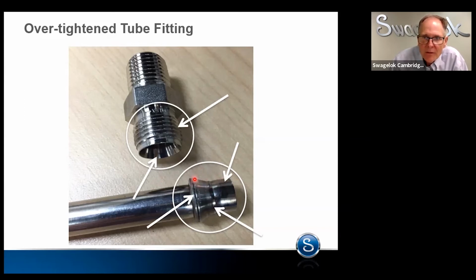But when you've over-tightened a fitting, if you make a fitting up correctly, this gap right here between the front ferrule and this rear ferrule, you can get your fingernail in between there. And you need that gap for retightening, because when we retighten, we're simply moving the nut and pushing the rear ferrule forward 12.5 thousandths to expand that front ferrule out to seal against that body bevel. When you over tighten, what we've effectively done is we've driven the rear ferrule into the front ferrule. We've effectively welded it into a one-piece fitting.